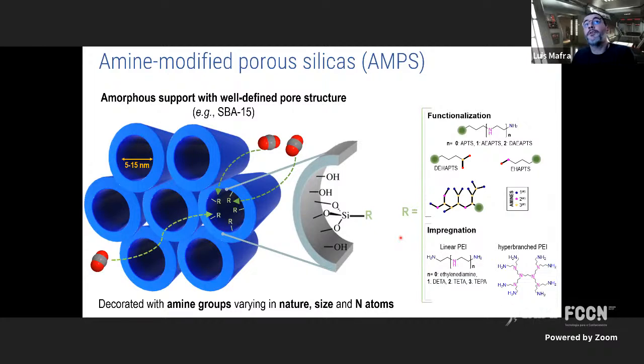They are 5 to 15 nanometers across, and they can be decorated with amine groups varying in density, nature, size, and so on. On the right side, I give you an example where you can graft different amines with different bulkiness, different sizes. If it's too big, of course, you have less pore volume. Instead of grafting, you can also physically impregnate different polymers, okay? And these are just 2 examples. There are a plethora of different molecules you can just put inside the pores.